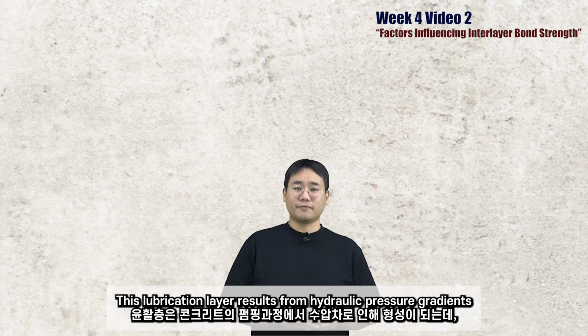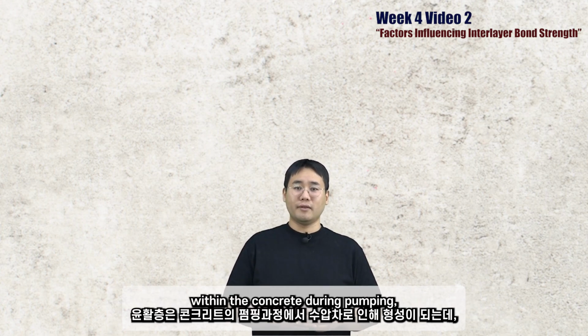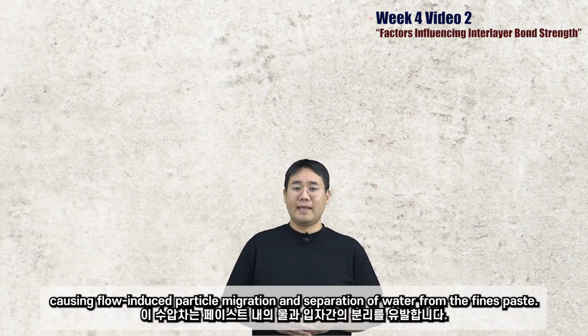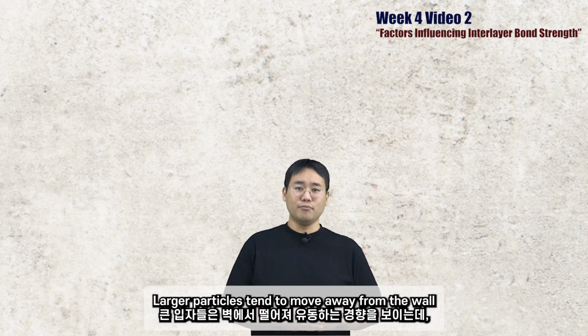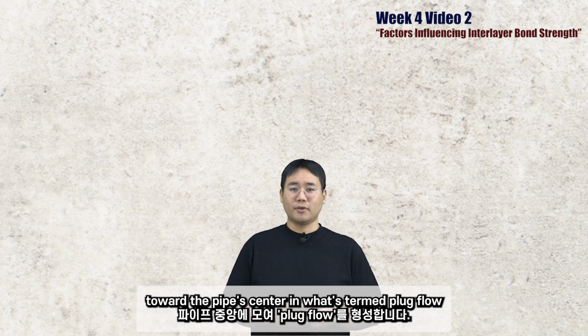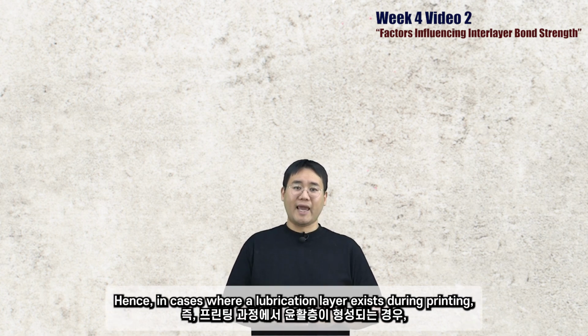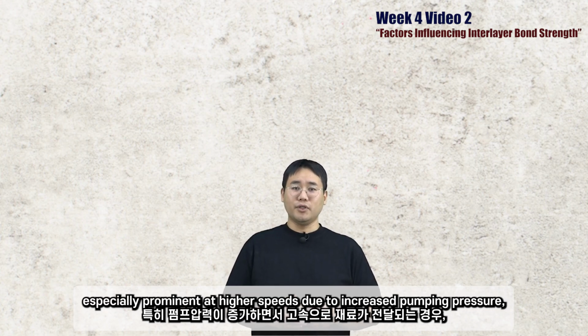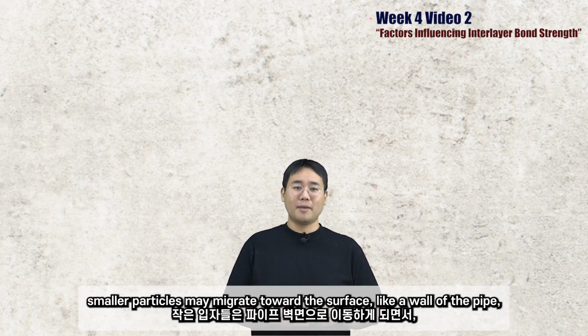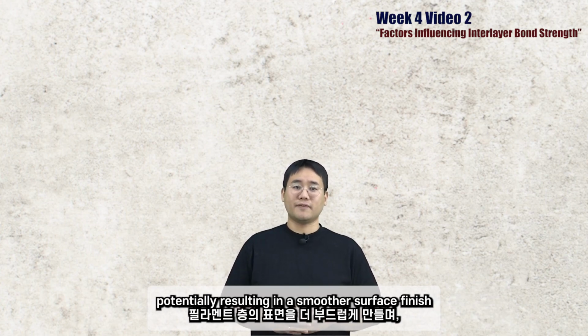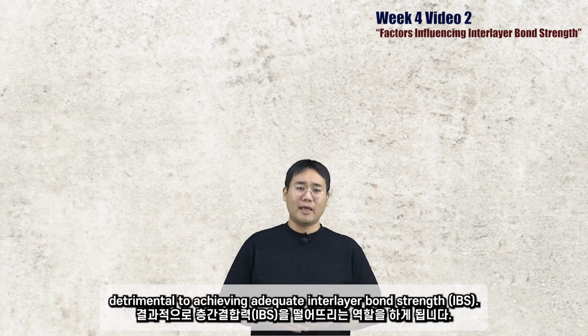This lubrication layer results from hydraulic pressure gradients within the concrete during pumping, causing flow-induced particle migration and separation of water from the fine paste. Larger particles tend to move away from the walls towards the pipe center in what's termed plug flow. Hence, where a lubrication layer exists during printing, especially prominent at higher speed due to increased pumping pressure, smaller particles may migrate towards the wall of the pipe, potentially resulting in a smoother surface finish detrimental to achieving adequate interlayer bond strength.